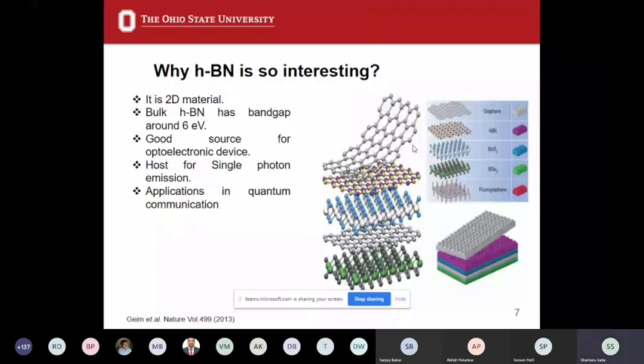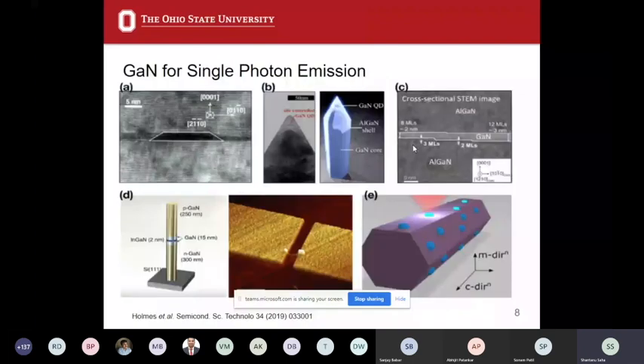Apart from hBN, we are also working with gallium nitride. Now we can see in figure B, this is a gallium nitride core-shell, AlGaN/GaN. AlGaN has a higher band gap, so AlGaN is working as the shell structure, which is protecting the inner gallium nitride. And there is another gallium nitride quantum dot. So the quantum dot will actually emit the single photons. Apart from that, in figure D, you can see that people have also worked with GaN/InGaN nanowire quantum dots, where the InGaN will emit the single photon. And in figure C, you can see this AlGaN is working as a barrier, while your GaN is the core structure.